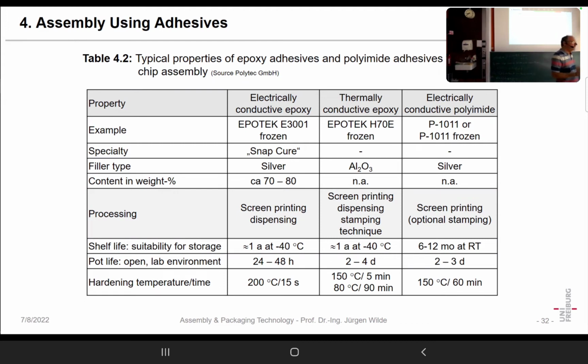We all have seen the Arrhenius equation, which describes that behavior, which is an exponential behavior. And we need that. And for that, we have a so-called shelf life. So we can keep such an epoxy, for example, for 1 year at minus 40. Of course, storing at such low temperature is not so cheap, but in the end, it's manageable.